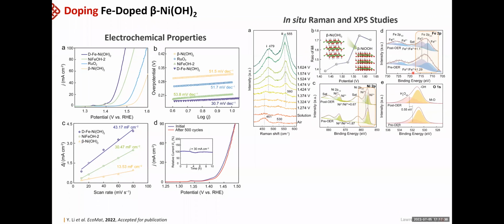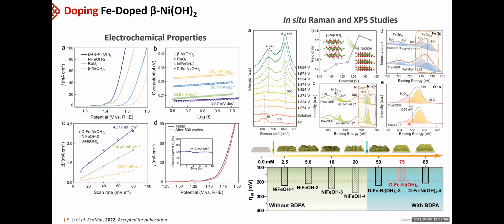We can see that the nickel 2+ to nickel 3+ and also iron 2+ to 3+ ratio drops, gets smaller, which confirms the formation of high valent species. And in the oxygen species, we also see that after the OER experiment, the peak for the observed water species gets higher and shifted, which means this surface has a very hydrophilic nature, so that it can actually do better catalytic reactions. So this is the main finding.